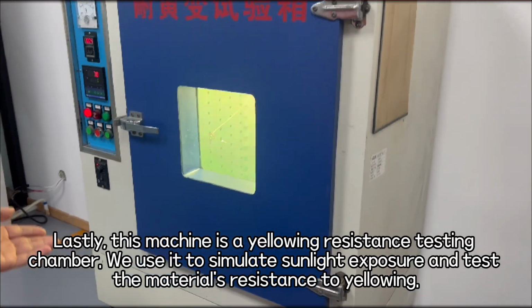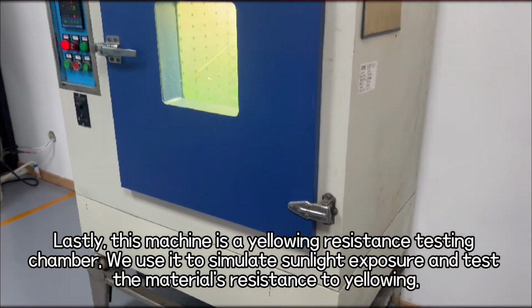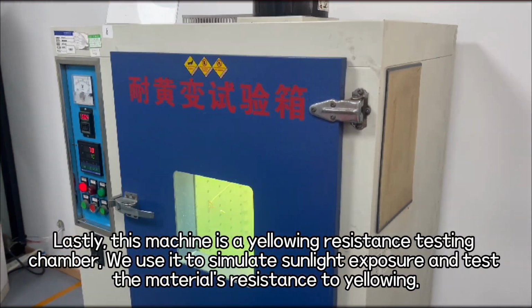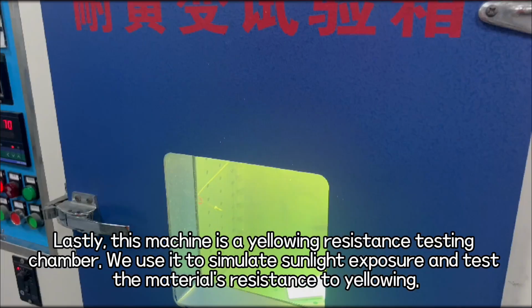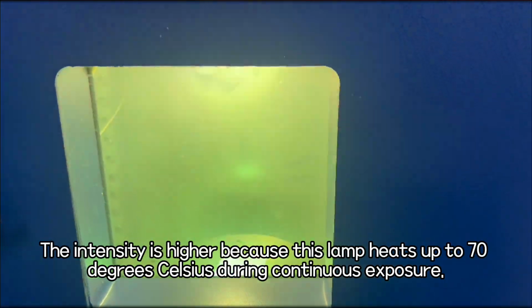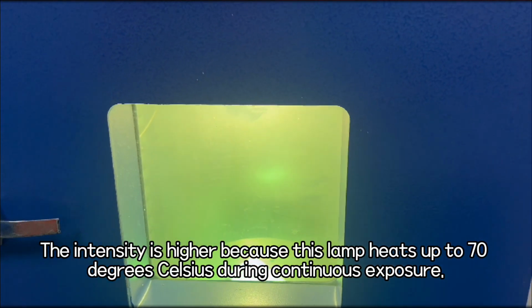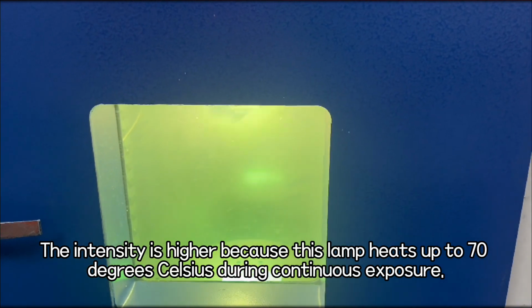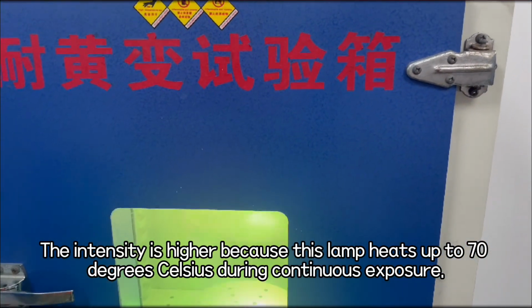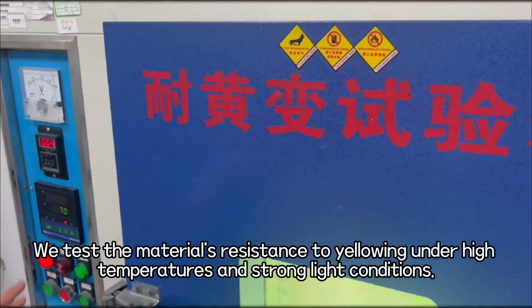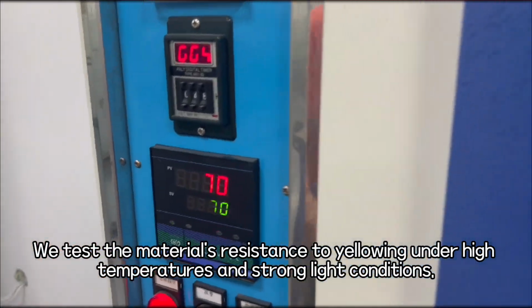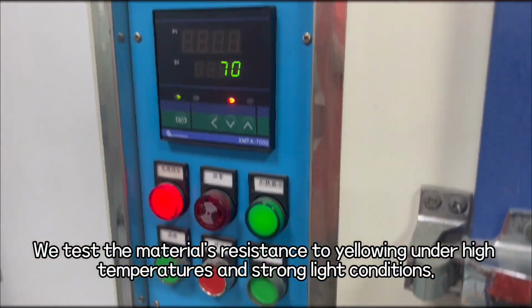Lastly, this machine is a yellowing resistance testing chamber. We use it to simulate sunlight exposure and test the material's resistance to yellowing. The intensity is higher because this lamp heats up to 70 degrees Celsius during continuous exposure. We test the material's resistance to yellowing under high temperatures and strong light conditions.